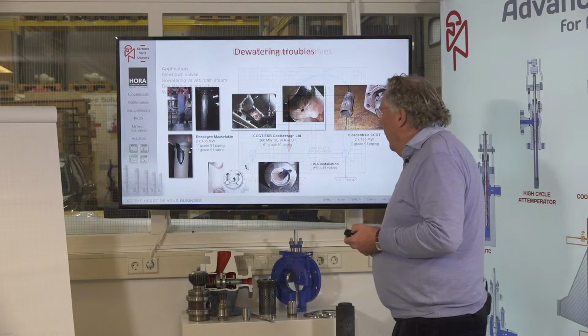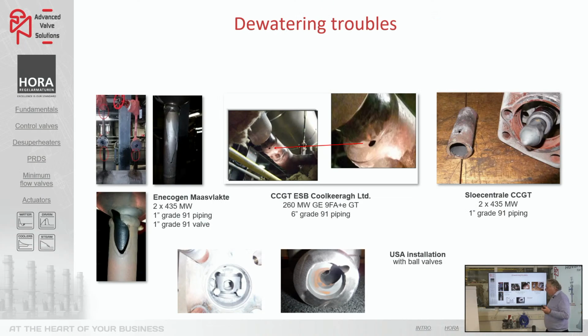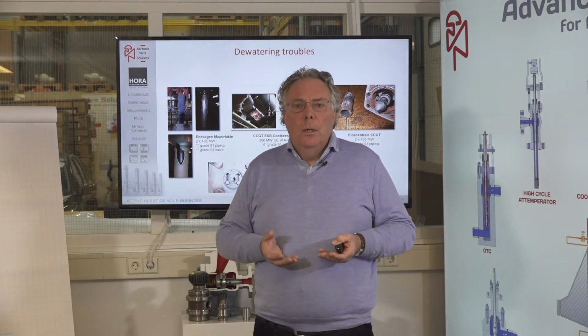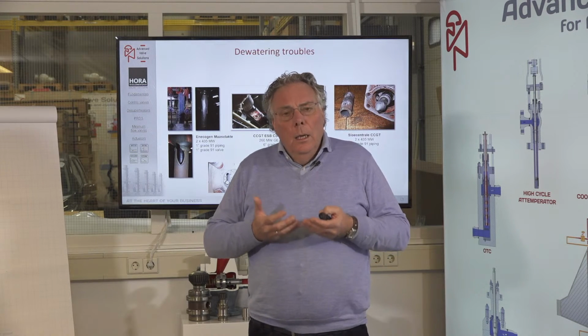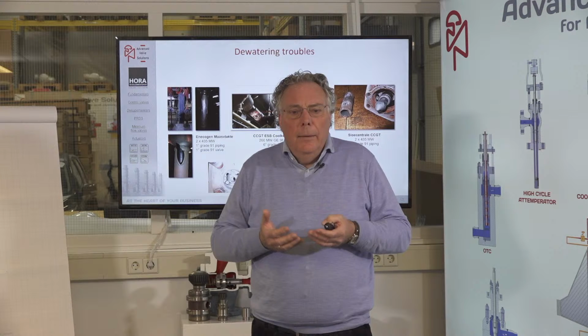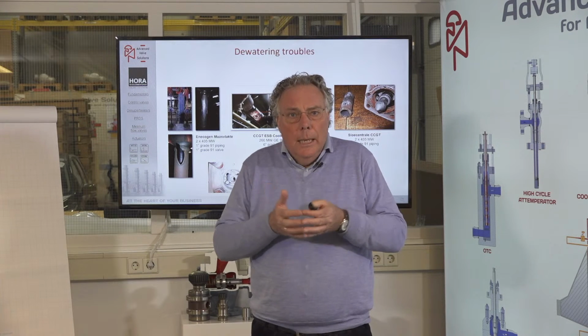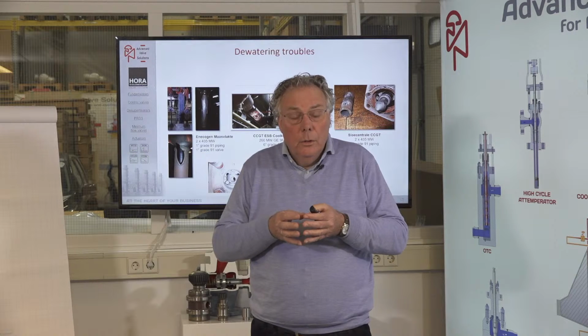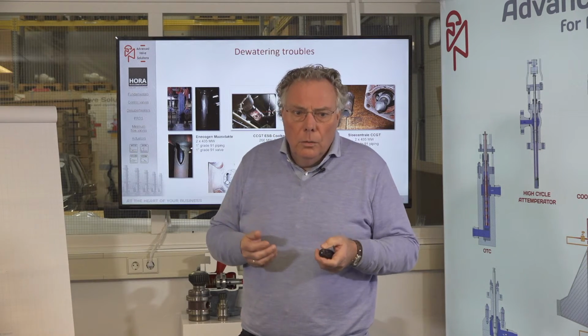And honestly, we have a whole collection of nice pictures of all kinds of damaged drain valves. You can see you really get enormous holes in the material, and that is not the best way forward. Why? Because then you have a leaking valve, you cannot maintain pressure in your boiler, and that is one of the features of what we can achieve if we can close the boiler, if we can lay up the boiler overnight when it doesn't have to run. We can then close it, and with that, when the boiler is closed, you can maintain the pressure and you can make a hot start or a warm start in the morning instead of a cold start.